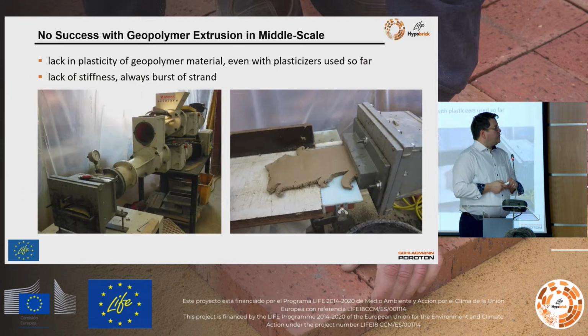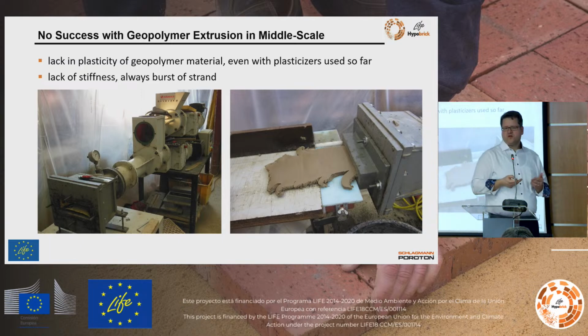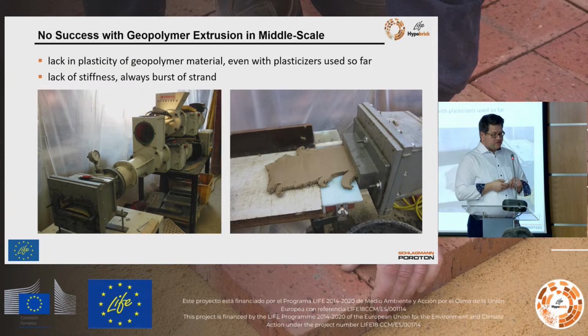So when we then started to extrude geopolymeric paste, we saw the lack of plasticity and stiffness, which we need, of course, for the green brick or green strand, freshly extruded. It is really hard work, a hard task and a hard challenge, to extrude even at a middle scale. And for us it was clear that if it is not working in a middle-scale extrusion, where we usually make new clay formulations, which is also usually not easy to extrude and to have enough plasticity and stiffness, then we cannot go to industrial scale.